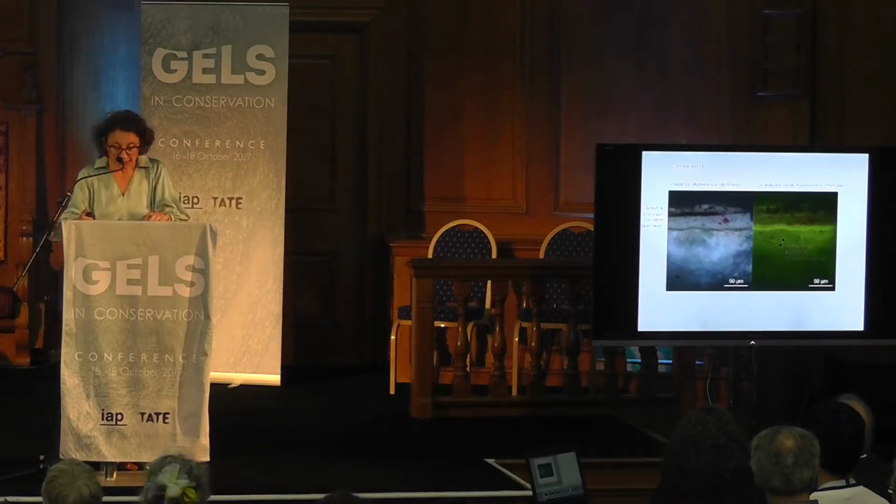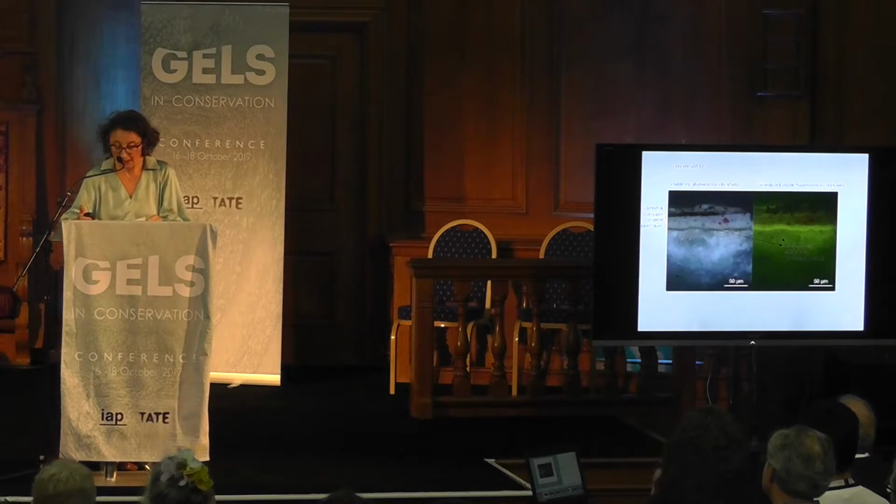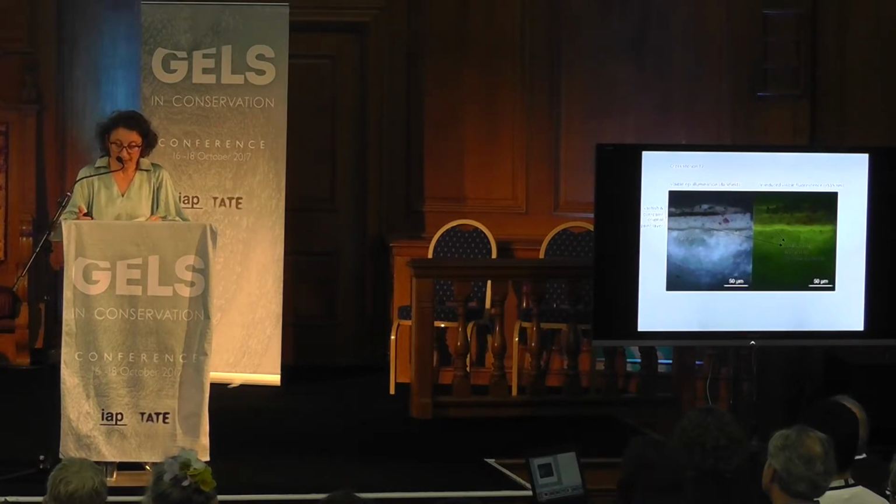The imprimatura layer is followed by a drying oil-based paint layer. In this cross-section, it consists primarily of a lead-white pigment matrix with few red lake pigment particles, coarse carbon black, dark iron oxide pigments, and a few silica and aluminosilicate particles. Darkened varnish and pigmented layers follow.